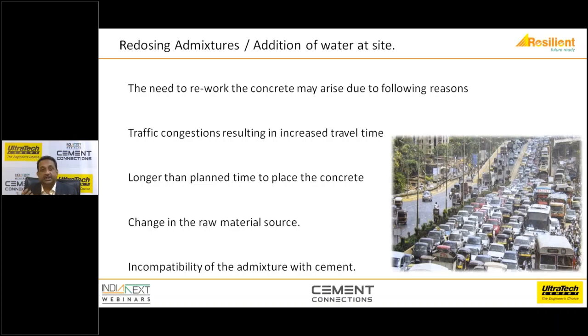Another reason could be the change in raw material source. If you change the cement type or cement suddenly, then you might land up with too much of fines or C3A content or C3S content. Anything can actually have developed incompatibility with the admixtures. Or high fines in the sand can also create this. So any change in the raw material source will create problems over here. And incompatibility of the admixture and cement also is a large contributing factor here.